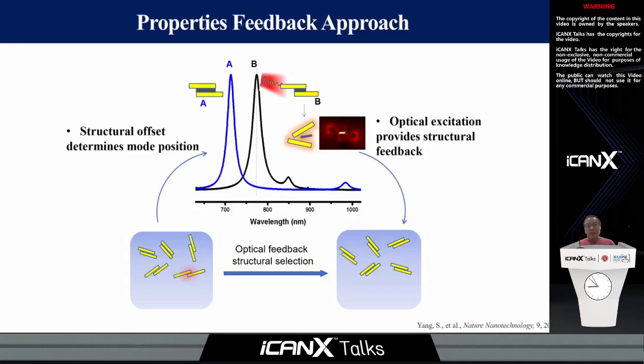Now, if we excite one of the structures, let's say the B structure in the system, the resonance will generate hot electrons. The hot electrons will relax and have a photothermal effect that will dissociate the bonding between the two nanorods of the B structure. In other words, the excited B structure cannot be assembled in the system in the chemical self-assembly process. In this sense, if we sweep the wavelengths, we can control which structures are not assembled and only the designed structure remains to be assembled in our system.